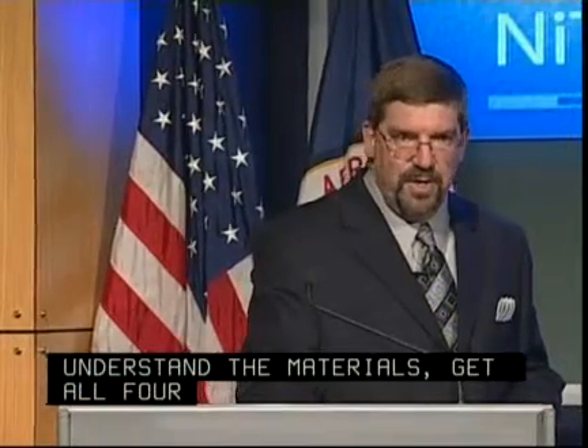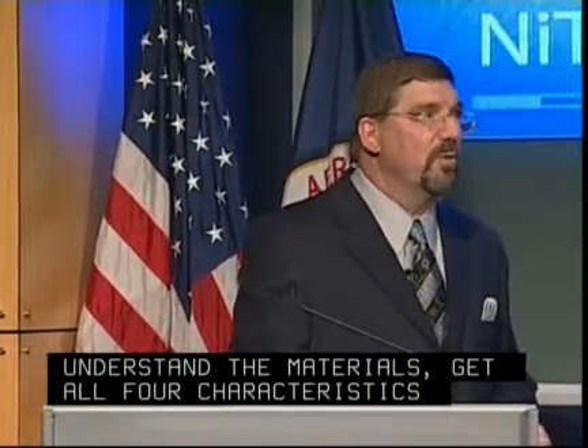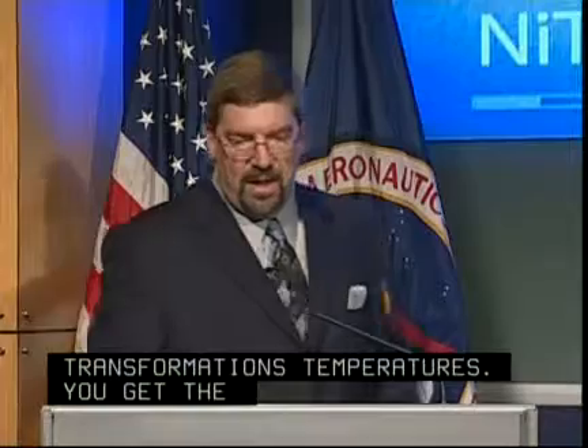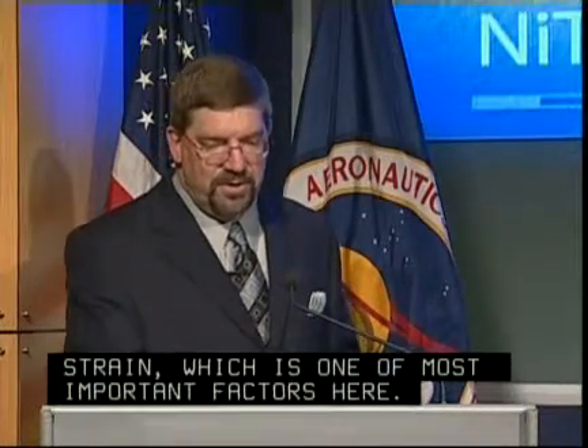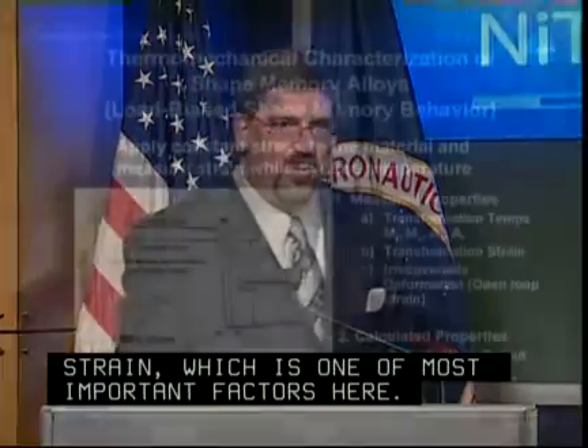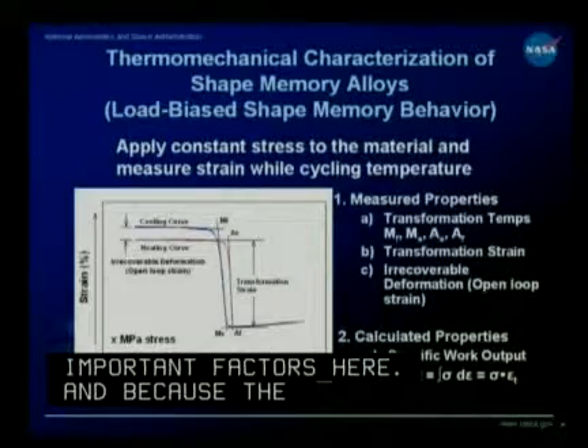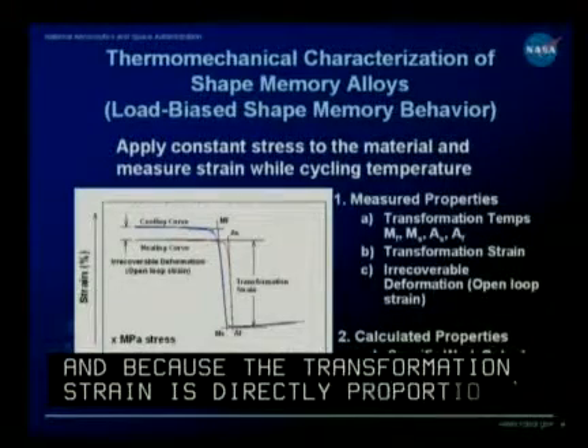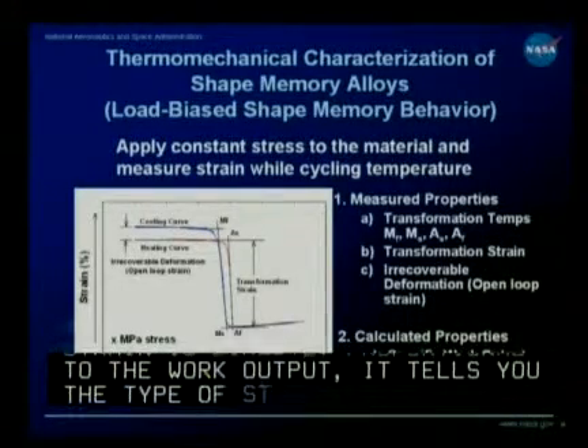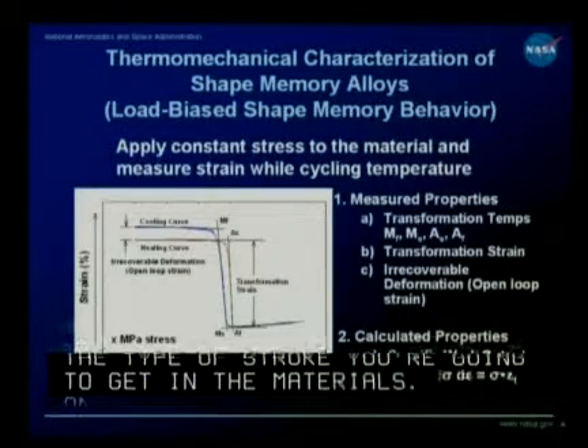transformation temperatures. You get the transformation strain, which is one of the most important factors here. And because the transformation strain is directly proportional to the work output, it also tells you the type of stroke you're going to get in the materials. And you also get something known as irrecoverable deformation if those loops don't close up.